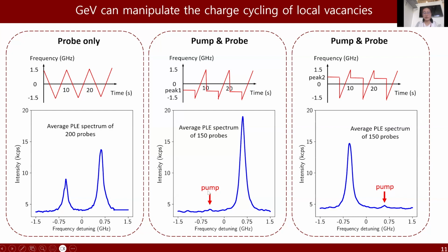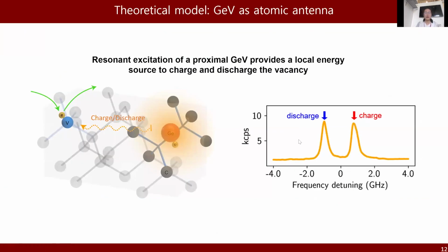We can also park the laser on resonance with peak 1 and pump it for 5 seconds, followed by a 5-second probe scan, and we repeat this laser sequence 150 times. In the end, we only see peak 2 in the average PLE spectrum, which means that peak 1 never shows up. And vice versa, we only see peak 1 if we repeatedly pump peak 2. This experiment indicates that the resonant excitation of a GeV can provide a local energy source to charge and discharge the nearby carbon vacancy. In other words, the GeV is functioning as an antenna to control the charge state of this nearby vacancy.